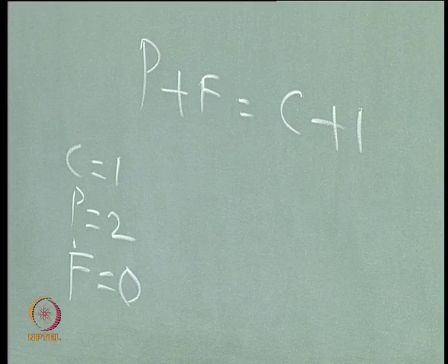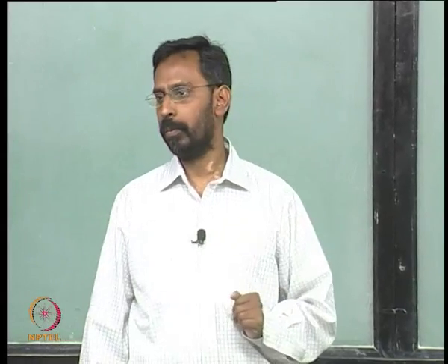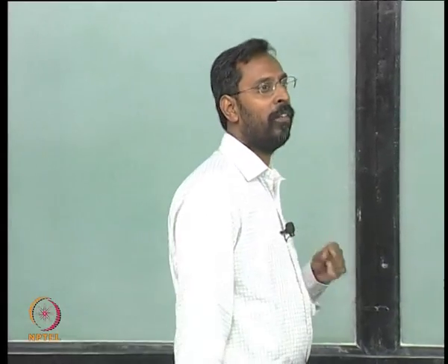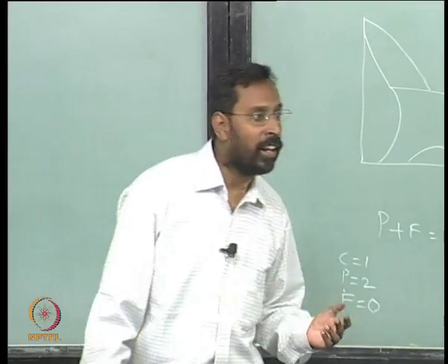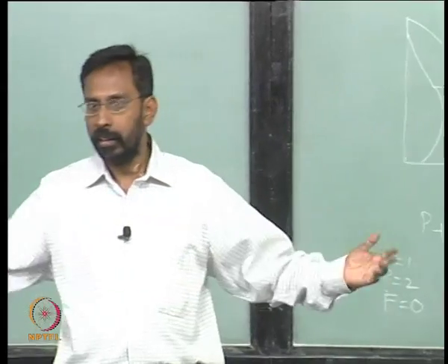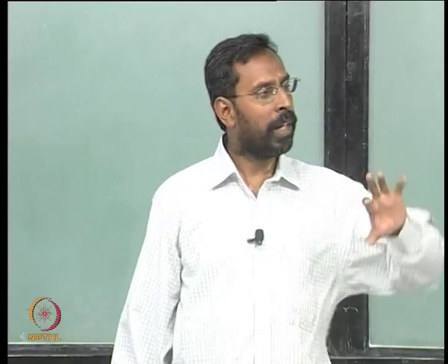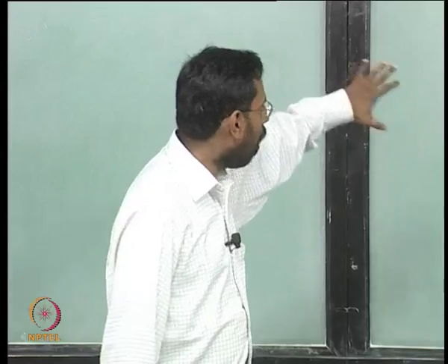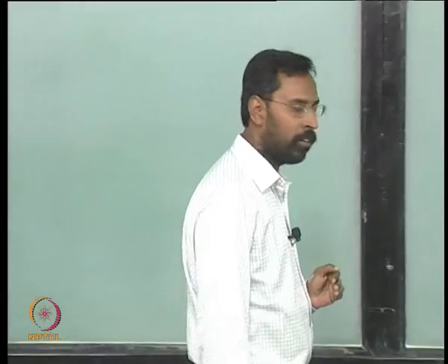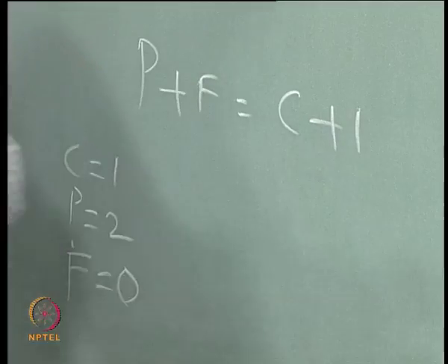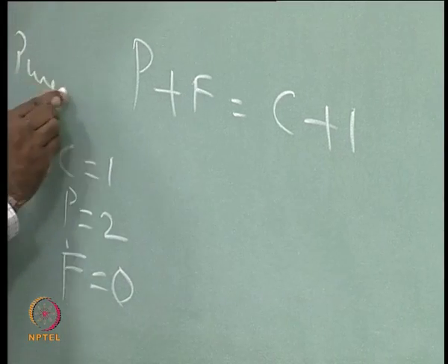one phase changes to another phase, whether it is a solid state phase transformation, solid to liquid or liquid to gas, whatever, is 0. The only thing is, when you are talking of liquid to gas cases, we usually do not use the condensed phase rule, we use the generalized phase rule, where P plus F equal to C plus 2, and bring in the effect of pressure. Whereas in all these phase diagrams that we talk about, pressure is always kept constant. Because pressure is kept constant, we use the condensed phase rule, and once we use the condensed phase rule for any pure component, like for a pure metal,